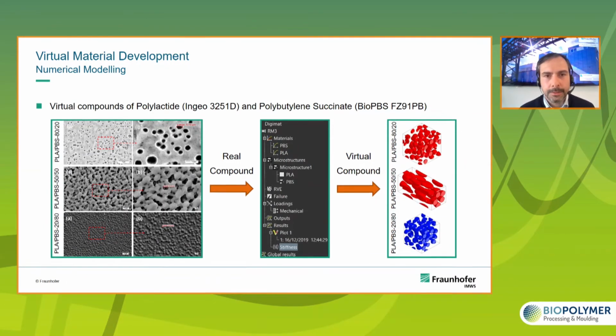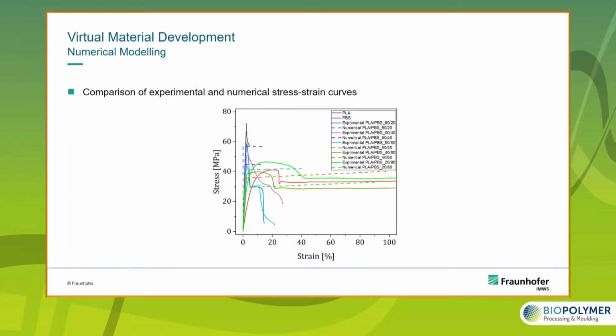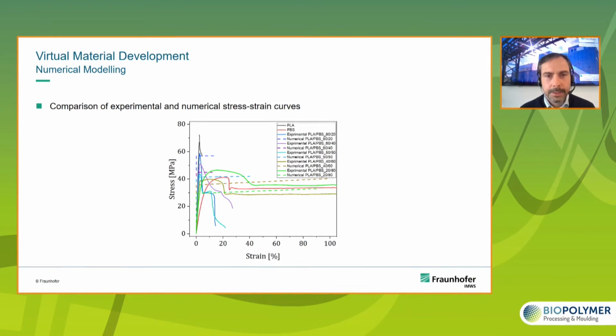This information was transported by numerical modeling into virtual compounds, meaning we created the virtual microstructures, which are shown on the right side. And for those materials, we did numerical simulation of the tensile test, and you can see the results here. We actually got very good overlapping of the predicted, meaning numerically simulated, material behavior and the experimental material behavior during the tensile test of our blends. You can see that especially at lower strains, this overlaps very well. At higher strains, the numerical simulation does not 100% overlap with the experimental results. This is something we will work on to optimize our material models and the prediction of the numerical simulations.